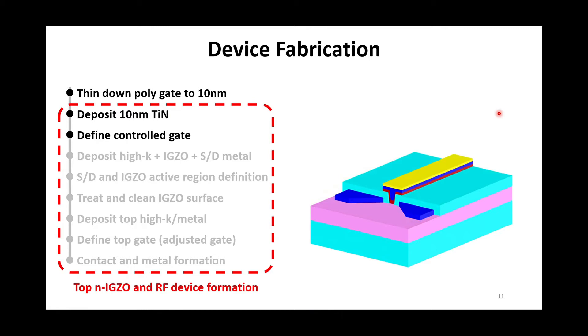Later, 10 nanometer hafnium oxide is deposited by ALD. Then IGZO and TiN was sputtered, and they were further defined as the top active layer and source-drain electrodes respectively. We chose the gas with and without fluorine to etch the source-drain electrodes. They will be discussed below.